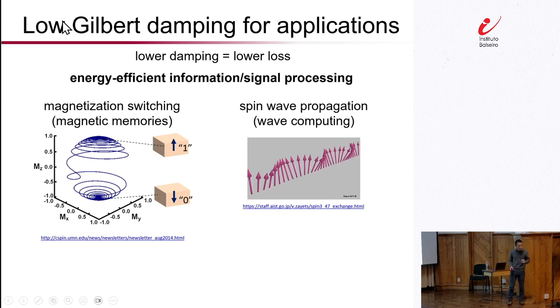On the other hand, there are also other types of devices where there's really no trade-off. You just want to minimize damping as much as possible. These are devices where you would be using spin waves, or some of you may recognize that term as magnons. It's a rippling, wave-like dynamics of magnetization in a magnetic material. By having low damping, first of all, you can initiate a spin wave with a lower amount of energy input, and furthermore, the spin wave can propagate over longer distances with lower decay, lower dissipation. So here, low damping is good all the way around.